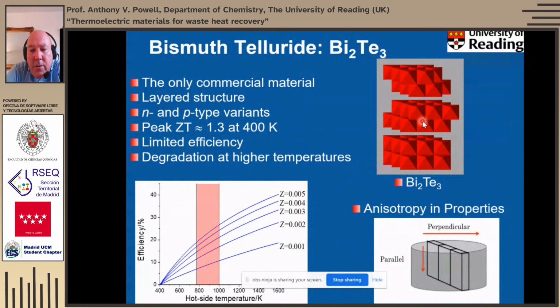That in itself can introduce some problems because it means that the properties are generally very anisotropic. And often in terms of powder consolidation, where we're pressing an ingot, we need to be able to cut that ingot in particular ways in order to measure the transport properties, both parallel and perpendicular to the pressing direction, because the anisotropic structure gives us an anisotropy in terms of properties. The nice thing about bismuth telluride is that it's possible to make chemically compatible N and P-type variants. If you remember, the thermoelectric device has both N and P-type semiconductors, so we could make both N and P-type versions of it through suitable doping.